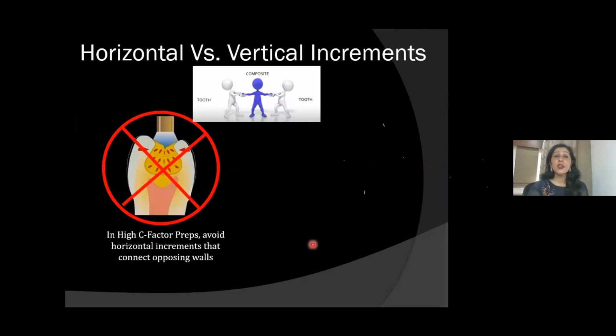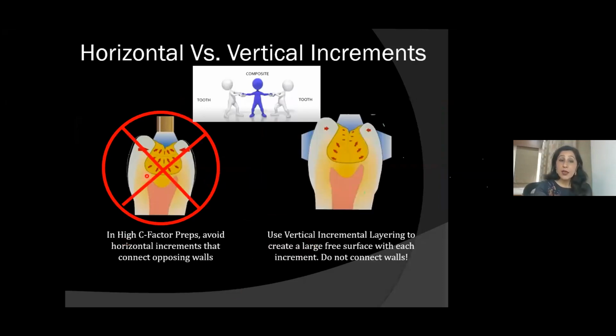So when you place horizontal increments, what happens? The composite is in between, and the tooth wall is here, the tooth wall is here. So on both sides, the composite is attached to the tooth walls. When it polymerizes, because of the polymerization shrinkage, there's a lot of polymerization stress induced in the composite at that time. So what does it do? It imparts this stress to these walls. This causes a lot of stress to the tooth walls, so much so that sometimes your walls may craze or fracture. You can see craze lines, fracture lines, or the restoration may fracture. That means the stresses are so much that your restorations can fracture. And if you can avoid this, why shouldn't we?